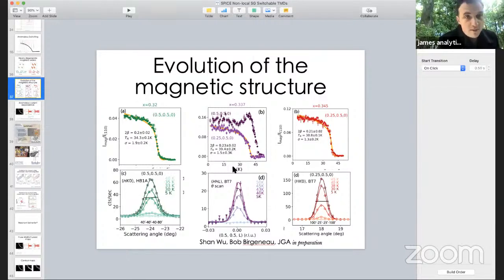My experience in other inversion breaking systems, like the skyrmion type systems, is that you always get some incommensurate structure on top. So I was hoping that that's what would happen, but actually we don't have any evidence for it. The neutron scattering hasn't seen any incommensurate in-plane structure.